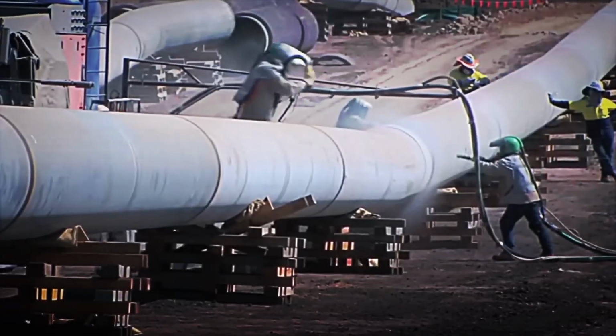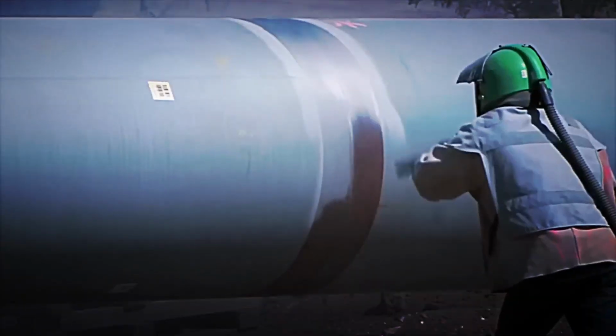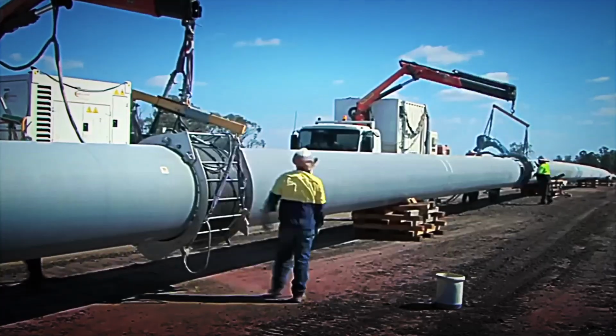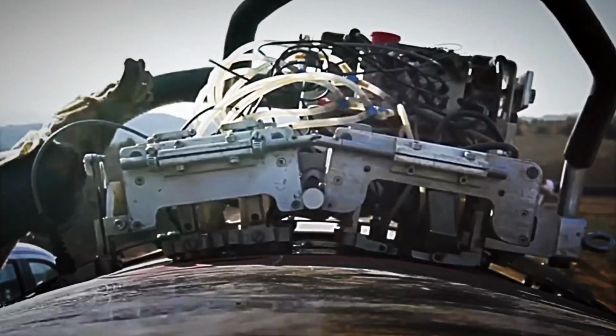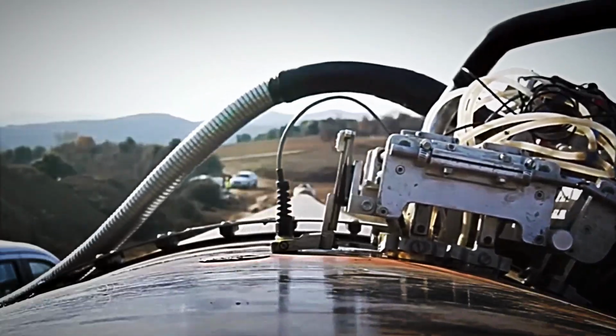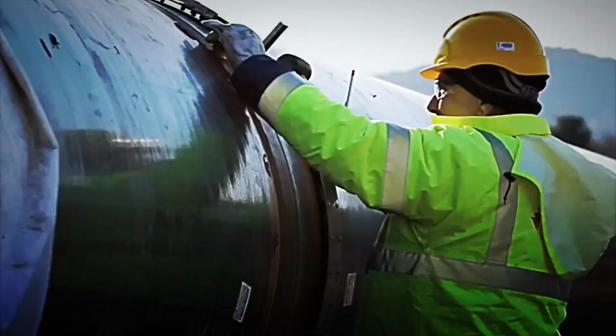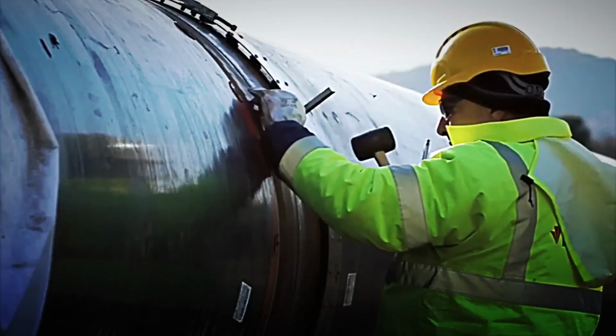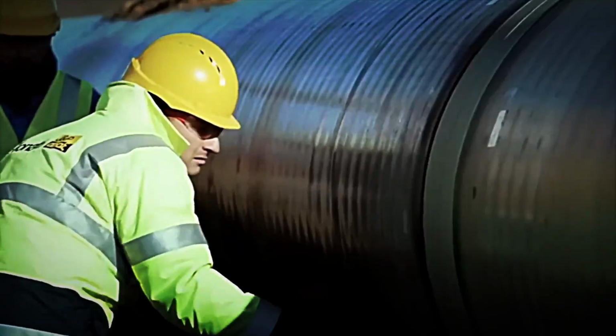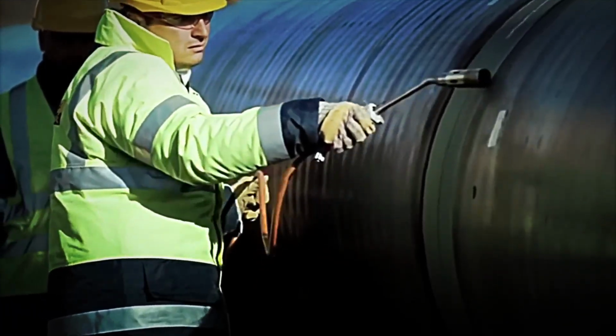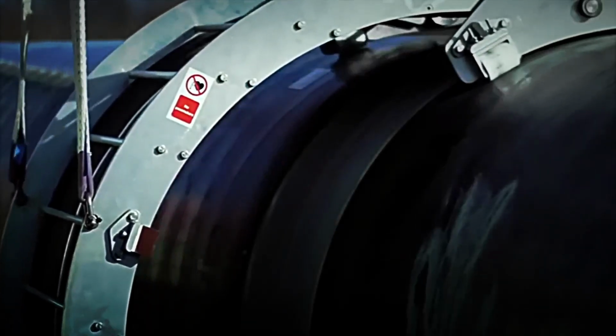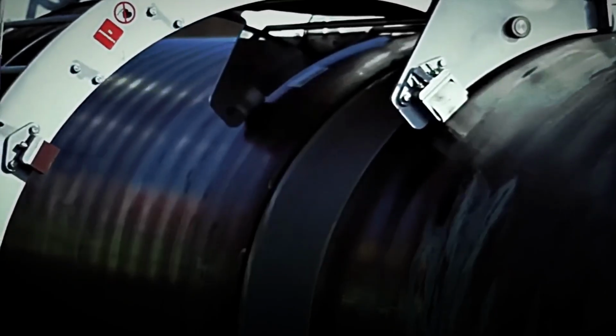In the welding area, a hydraulic clamp is placed inside the joint and expanded with gripping pads that surround 360 degrees, keeping the two sections perfectly concentric and aligned before and during the first pass of welding. An automated operation is deployed, supported by a team of around 80 people and dozens of specialized machines, capable of completing up to 150 welds per day on 42-inch diameter pipes.